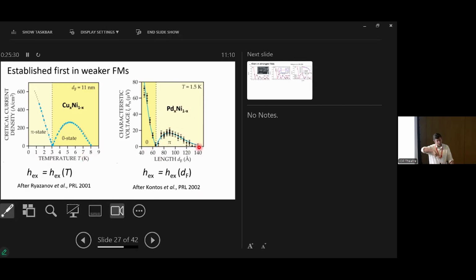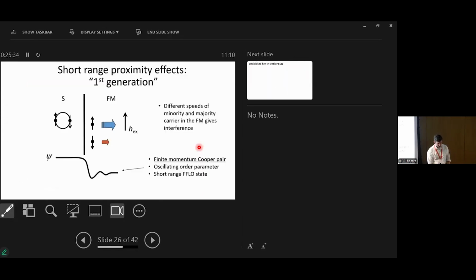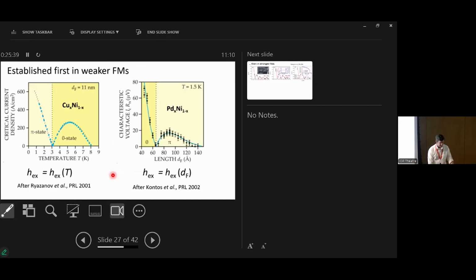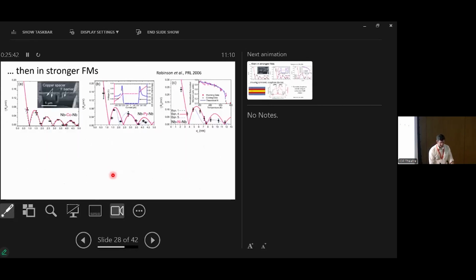So this non-monotonic shape is essentially the same as this oscillating order parameter. You can think of it like that. So we're mapping out that. So that was very nice. We established it later in stronger ferromagnets, cobalt, permalloy, nickel. And this was a bit more challenging because the distances here now are just a few nanometers.